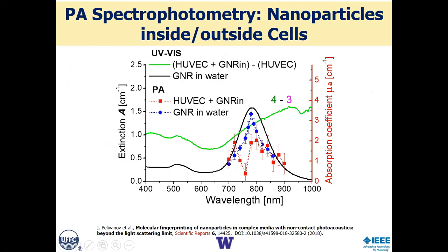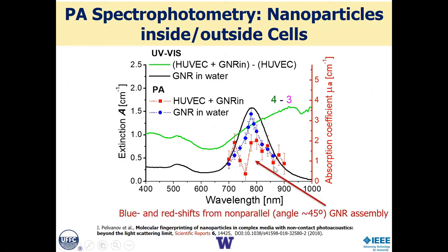Here is the spectrum we get when the nanoparticles are outside the cells. This is the spectrum we get when the nanoparticles are inside the cells. And this is a very real physical effect: when they're inside cells, these nanoparticles are endosomally captured, so they're very closely packed. And so you can get plasmonic coupling between the nanorods. That's why we pick rods, which can couple this way or this way. Those two different modes split, one providing a red shift, one a blue shift. So by measuring the spectrum, we can differentiate between nanoparticles which have been captured inside the cells versus those outside cells. So again, true molecular profiling, but now done in this non-contact way, with non-contact optical detection of ultrasound.